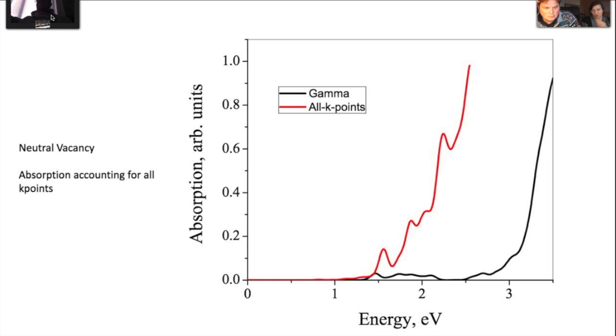You can see that when the initial onset changes slightly, when you get past 1 eV, the all K points has a little bit more intensity, but then everything jumps up at a relatively higher level. And I believe that's largely due to taking into account all these other transitions and showing a more realistic spectra compared to what we initially had.